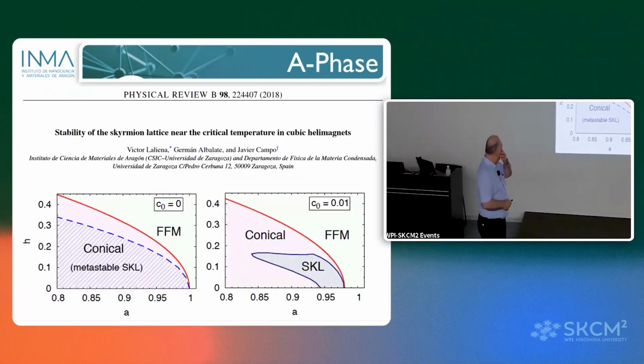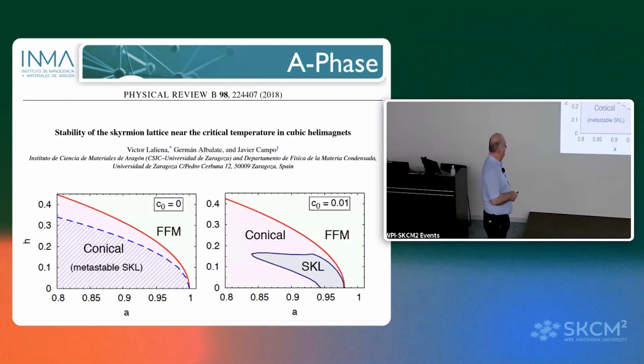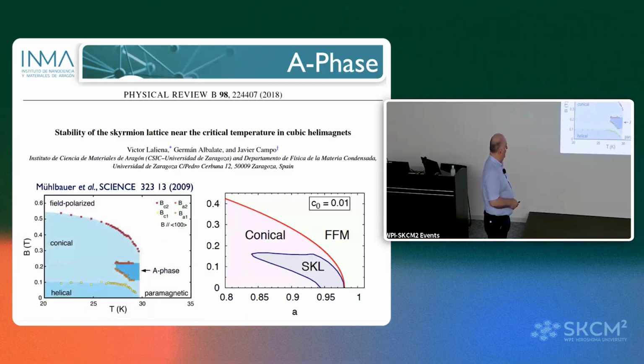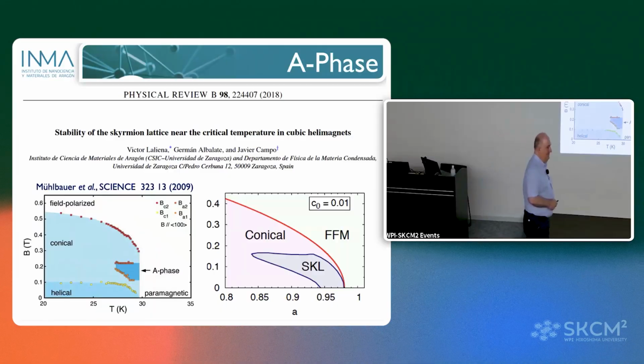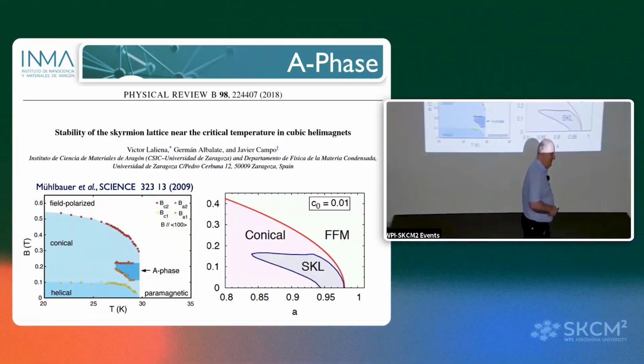By doing something similar, we were also able to understand how thermal fluctuations can stabilize the skyrmion lattice around the paramagnetic phase. We did this theoretical calculation without temperature and with temperature, and this was also in good agreement. And then let's go now to see the experiments.